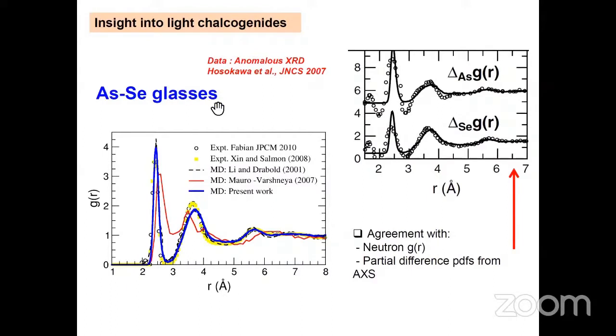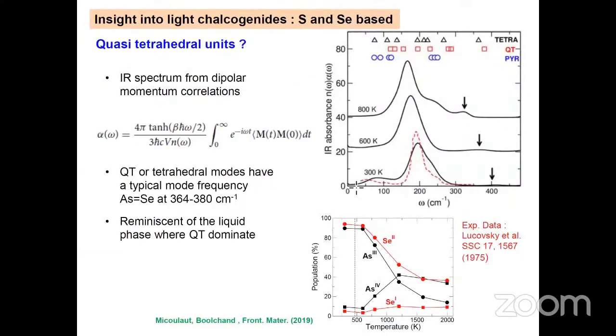For example, in arsenic selenium glasses, here you have the correlation function, which can be very nicely compared in blue with previous experiments in yellow, or the circles from Xin and Salmon or from Fabian and others. And you can also notice that it describes much better the structure as compared to a classical force field, like the one you see in red, which is from Mauro and Varshneya. It also agrees with partial correlations that you access from anomalous X-ray scattering. Here I show on the right side, on the top, a comparison, solid line, with respect to the circles which arise from experiments. The other interesting contribution on this system is that you can eventually calculate the infrared absorbance spectra.